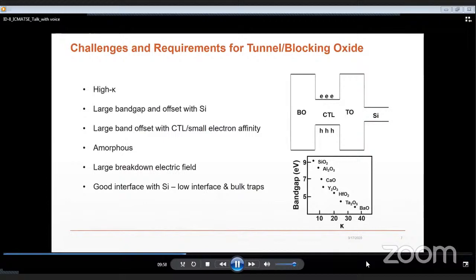The tunnel oxide material has to be amorphous since grain boundaries in crystalline materials act as leakage paths, which would deteriorate the retention of the memory. And the tunnel oxide should have a large breakdown electric field because when scaling down the devices, the electric field across the tunnel oxide drastically increases to reach several megavolts per centimeter. The tunnel oxide has to have a good interface quality with silicon, with low interfacial and bulk traps, which would otherwise cause reliability issues in the devices.